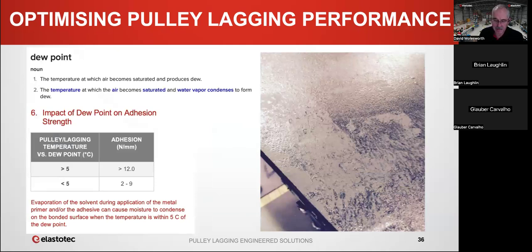Cold bond lagging is probably the most inconsistent of the three bonding methods, and there's a lot of variables. I'm not going to talk about all the variables, but one of the major ones, and Glauber, this we know is a problem in Brazil because of your tropical climate, but it's what we call the dew point. When you put the adhesive onto the surface of the pulley or the surface of the lagging, it's a solvent-based adhesive, and as the solvent evaporates, it creates a cooling effect. And that cooling effect can cause moisture to condense out of the air and onto the surface of either the lagging or the pulley. And you can see this photo on the right.